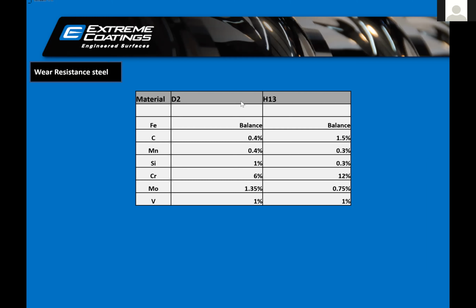Next level, as I said, there was D2 with some percentage of molybdenum and vanadium. It gives moderate resistance to corrosion, moderate resistance to the other two wears which we spoke about, adhesive and abrasive. But the limitation with these steels is that you cannot make a bigger size of screw. It's very difficult to remove the runout from those screws. So up to 36 mm, 40 mm, this is advisable. Yet this is not a foolproof solution.